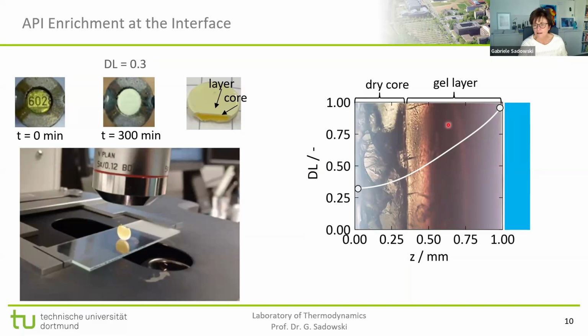So that means what happens is that during dissolution, water is absorbing and moving from the right to the left into the inner of this tablet, whereas in regions where the water didn't reach so far, we see more or less the ASD as it was at the beginning. And as a result of whatever happens here, and I will show you in the next slide what happens here, we end up with a layer which almost only contains the API, which is very hydrophobic and does not want to get dissolved anymore. This is where the problem started. And it's getting even worse for higher drug loads.